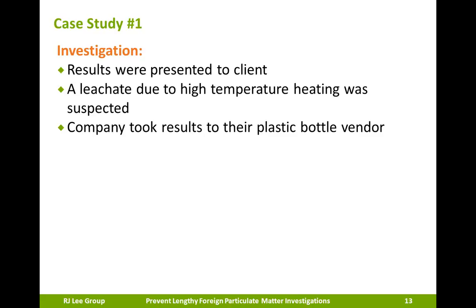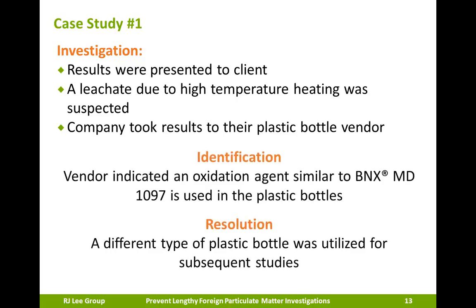At this point, we went back to the company and we presented these results, our findings. Through the discussion, it was suspected that these particles were possibly leaching out from the bottle containing the liquid during the incubation because of that elevated temperature. The company then went to the vendor of the plastic bottles. The vendor indicated that the bottles contained an oxidizing agent used as a polymer additive that was nearly identical in chemical structure to the BNX material. So therefore, for subsequent studies, the company resolved this issue by simply utilizing a different type of plastic bottle.